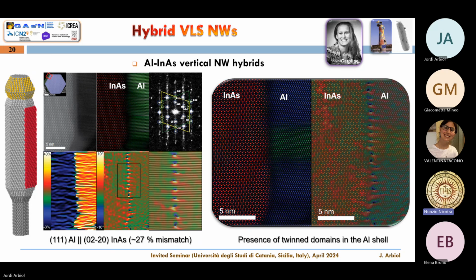The main problem is that from time to time, you create these twin boundaries. So the material tends to rotate 180 degrees, and you have many different boundaries. So maybe this is not super good for the idealistic properties you need. So it's not the mismatch at the end, which is 27%, which is a lot, because the material is all relaxed at the interface. A lot of misfit dislocations are relaxed in the material, and then it grows quite well. But the problem is maybe the formation of all these twin boundaries.